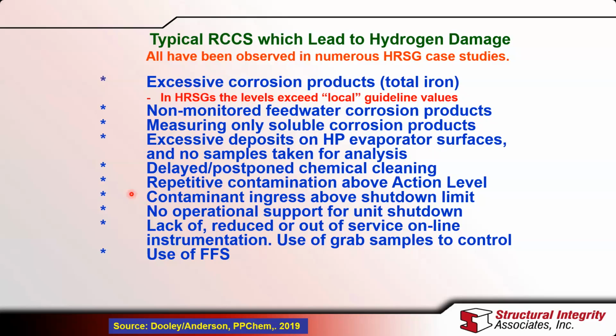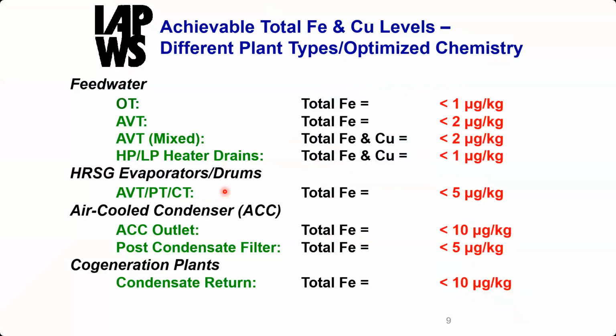And the other main aspect, the third part of hydrogen damage, is that there has to be some contaminant entering into the cycle. Usually in the form of chloride, or seawater in seawater cooled plants. And these contaminant levels are allowed to exceed the action level, the chemistry action level, or the chemistry shutdown limit. And so these are the main features: increased corrosion products, increased levels of deposits on the internal surfaces, and contaminant ingress. And so let's have a look at each one of these.